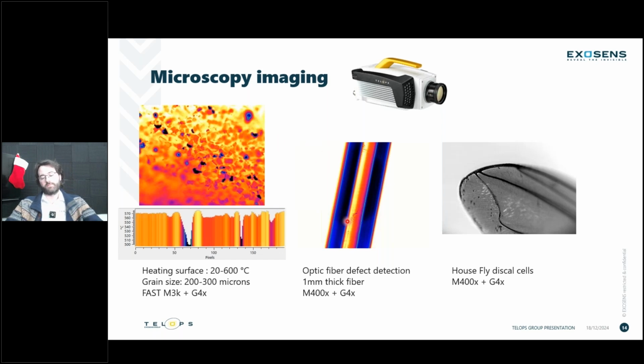Otherwise, we also did some optic fiber defect detection. So this whole fiber is only 1 millimeter thick, and we're able to look at non-uniformity stress that happened in the fiber or some defects. This group was looking at the option of doing even nanocrystal observations in infrared. So with that G4X microscope lenses, yes, we can see very well into the core of the fiber with a heated body. And in this case, it was a black body behind the fiber. And so you can really inspect the fiber and have the fiber roll in front of your camera at a relatively high speed to detect any kind of abnormality within your optic fiber.